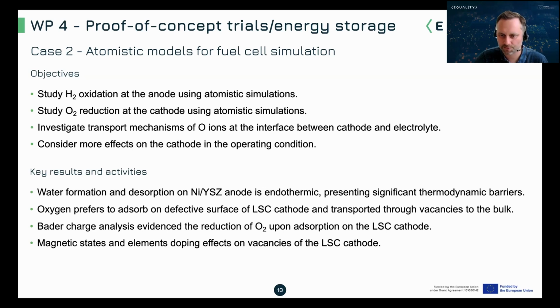Oxygen prefers to adsorb on the defective surface of the LSC cathode and is transported mainly through vacancies into the bulk. A Bader charge analysis revealed the reduction of oxygen upon adsorption on the LSC cathode, and magnetic states and doping effects on the vacancies of the LSC cathode material were studied in detail.